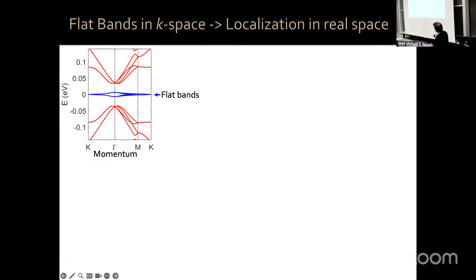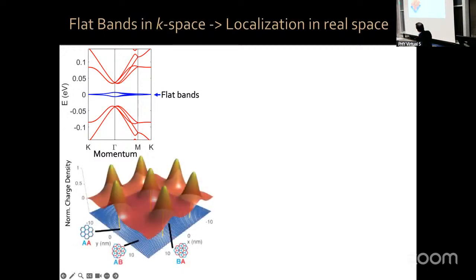Now, if we place electrons in these flat bands, where do they like to go in real space? To go from momentum space to real space, you do a Fourier transform, and the Fourier transform of a very flat object is a highly peaked object. So if you look at where the electrons in this flat band like to be, they like to sit in certain regions of the Moiré pattern.